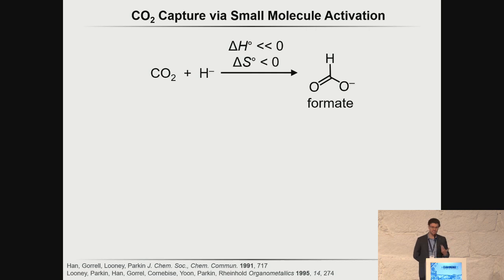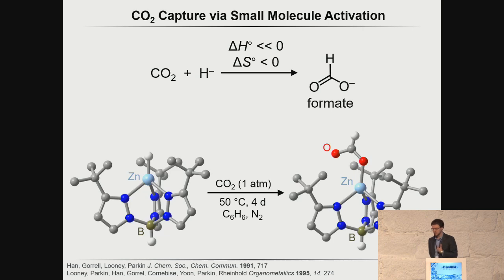And we thought about one of the simplest reactions, which is the addition of a hydride to CO2 to produce formate. This is an extremely common reaction, and I'm trained as a molecular synthetic inorganic chemist. And this is actually an easy way that our community tests for hydricity and the presence of a hydride. Simply, can you make a metal hydride, and can you react it with carbon dioxide? And our excitement here was this idea of potentially we could render this reaction reversible and then use this reversible metal ligand bond insertion as a mechanism to be able to undergo gas capture.